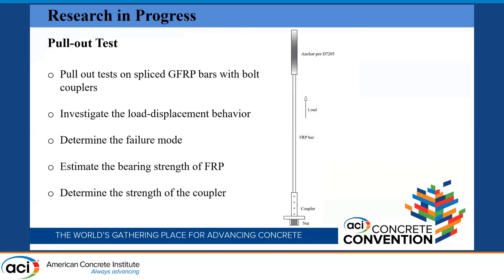The research and testing is still in progress. Pull-out tests are necessary to verify the performance of the spliced FRP bars with the couplers, to investigate the load-displacement behavior, determine the actual failure mode, and estimate the bearing strength of the FRP bars and the strength of the coupler. The goal is to reach the minimum guaranteed tensile strength of the FRP bars.